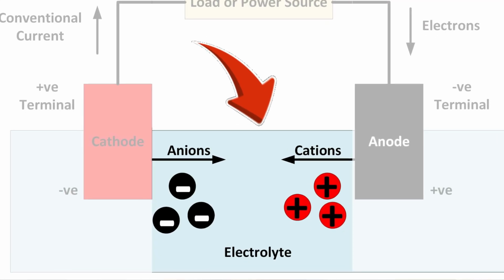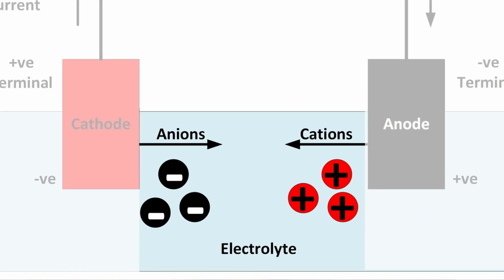On a chemical level, cold weather changes three big things. The electrolyte gets thicker and more sluggish. The solid layer that forms on the anode, called the SEI, becomes less forgiving, and the metal lithium itself wants to plate on the anode instead of folding neatly back into the structure during fast charging. Lithium plating is the real villain because it steals capacity and can start irreversible damage.